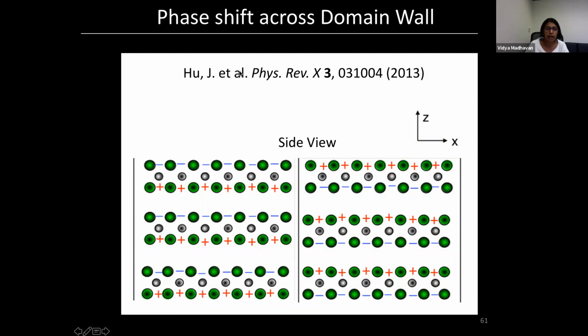This is a calculation done by Jiangping Hu in 2013, where they show that if you take into account the crystal structure, the nearest neighbor hoppings, next nearest neighbor hoppings, and so on, then the superconducting phase is as follows. This is a side view of the crystal. These are the tellurium atoms on top, these are iron atoms, and these are tellurium atoms below. So this is one layer. The pluses and minuses refer to the phase of the superconducting order parameter. That's what it looks like in real space. So if you could engineer the material where there's a physical flipping of the top and the bottom layer, then you would indeed get a pi phase shift right across this boundary.